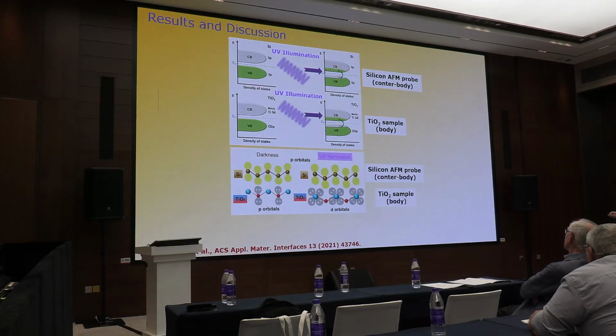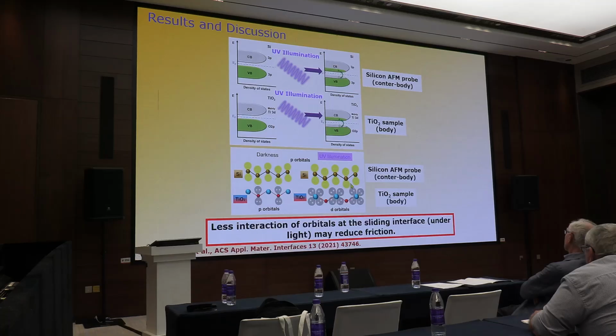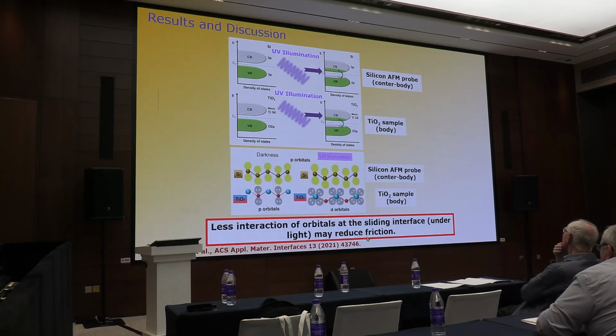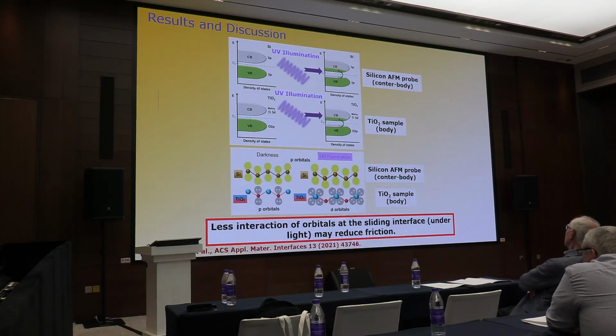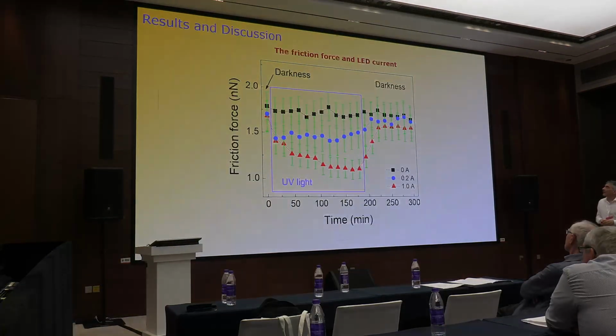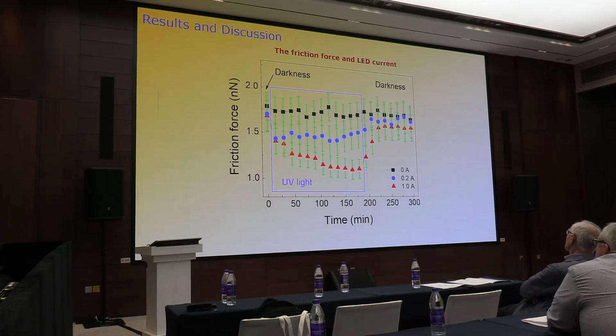Our interpretation is less interaction. We have this promotion of electrons with the UV, from the valence band to the conduction band. Less interacting orbitals at the interface may reduce friction. We modify the electronic density between molecular orbitals, and this reduces the friction. But this is the first interpretation. These are the latest results, unpublished results.